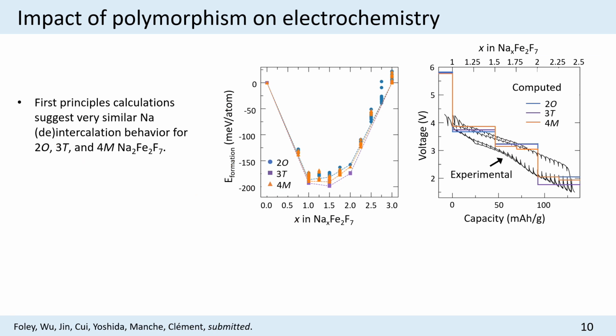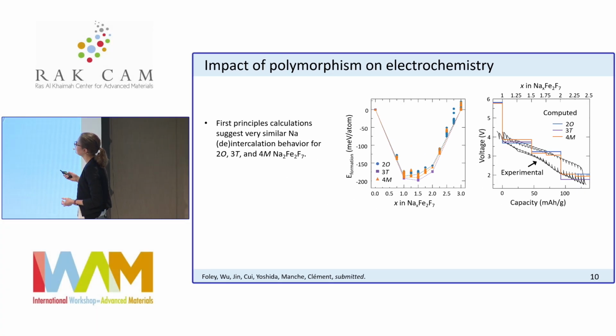But beyond what we find experimentally, we were also interested in what the polymorphism of this material does to the electrochemistry. Is there something we can learn just from first principles about polymorphism and the impact on electrochemistry? So here we decided to calculate the formation energies of various intermediate points during the charge and the discharge process. Here we're changing the sodium content in our Weberite structure from Na3 to Na0, simulating what we would get if we were to charge and discharge fully this material. And we're doing this for all 3 polymorphs here.